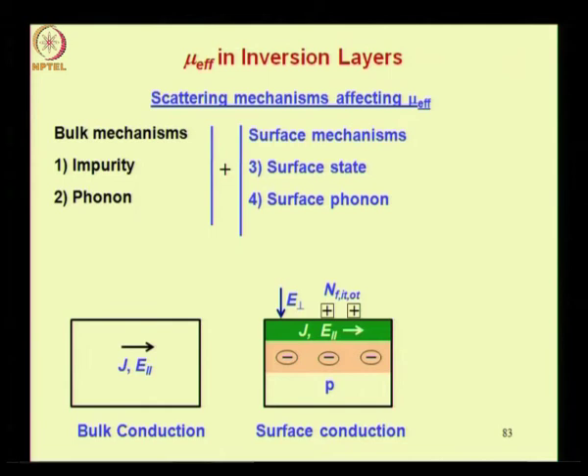You have analogous extra scattering mechanisms at the surface. For example, analogous to the impurity scattering, you have the surface state scattering because of surface charges. So, these charges are indicated here. They scatter the carriers in this surface mobile carrier layer just in the same way as you have scattering because of ionized impurities. Similarly, the phonon scattering in the bulk has an analog at the surface, and that is called the surface phonon scattering. In addition, you have a mechanism called surface roughness scattering, which is related to the roughness of this surface.